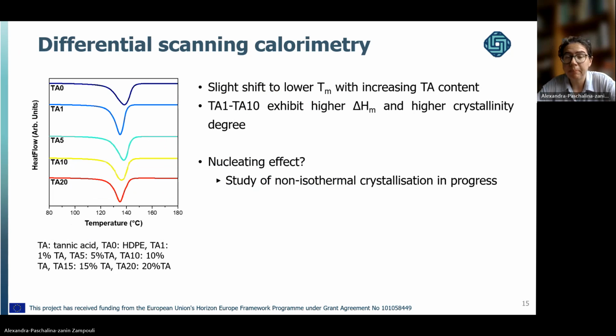Differential scanning calorimetry evidenced a slight shift to lower melting temperature with increasing tannic acid content, and also the composites with 1 to 10% of tannic acid exhibited slightly higher melting enthalpies and a higher crystallinity degree. This could potentially be attributed to some nucleating effect of tannic acid. Nevertheless, generally speaking, HDPE is a polymer with fast crystallization kinetics. So we will investigate more about this potential nucleating effect by studying non-isothermal crystallization.